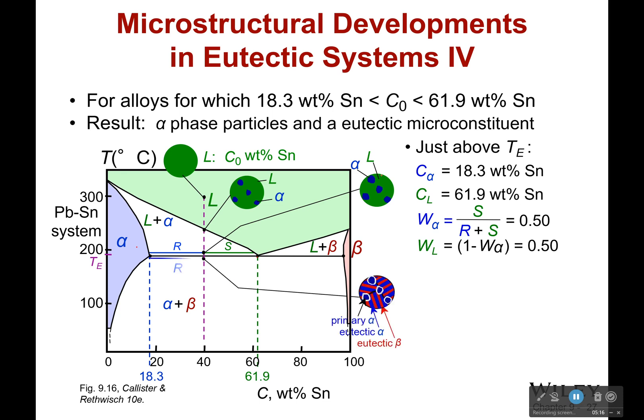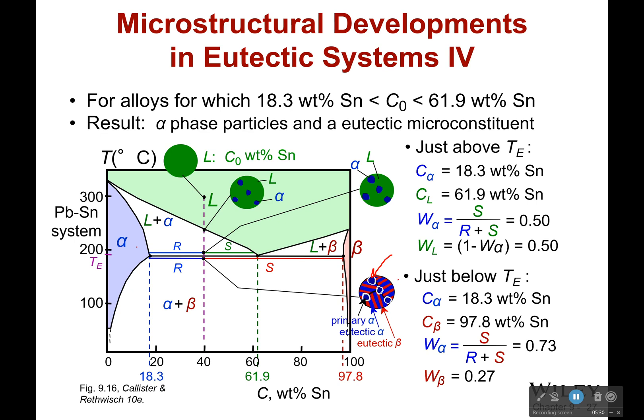And then I cross that line and what you're going to see is I will have two different types of grains. I will have my pure alpha grains, but then I will also around that have that eutectic microstructure, the pure alpha grains and then that eutectic microstructure. And it's kind of amazing how much of a change happens here because just above that eutectic temperature, my weight fraction of alpha and liquid is 50%.